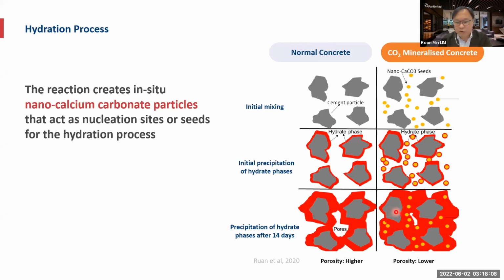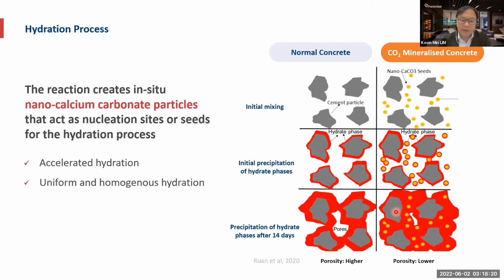And because of this reaction, it actually gives rise to three very important benefits. First one, it helps to accelerate the hydration. It gives a more uniform and homogeneous hydration in the concrete mixture. And last but not least, it reduces the porosity, as you can see over here at my cursor. Look at the pores for the normal concrete and also the pores that are being reduced for the CO2 mineralized concrete.